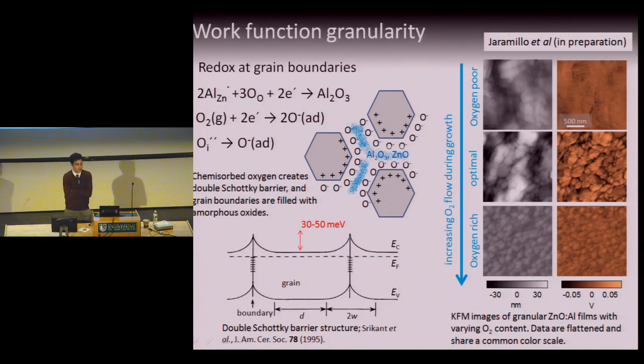However, you can do more. I mentioned that this is done with an atomic force microscope, which means that I don't just measure the work function of the material on a macroscopic basis. I actually have a high degree of resolution over the nanostructure of the work function. In particular, this is a sputtered material. It doesn't go down as one smooth, perfect single crystal. It's highly granular. So it's a bumpy material. You have crystallite grains, and they have grain boundaries. Those are non-crystalline interfaces. And what I found is actually really cool.